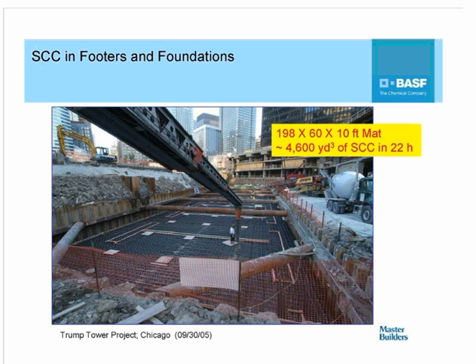Self-consolidating concrete has also been used and is being used quite extensively in mat foundations. It was used on the Burj Khalifa in Dubai, and in the U.S., Skidmore, Owings & Merrill also specified it for use in the Trump International Tower and Hotel project in Chicago back in 2005, where a total of 4,600 cubic yards of self-consolidating concrete was placed in a total of 22 hours continuously. The mat was 198 foot long by 60 foot wide and 10 feet deep.